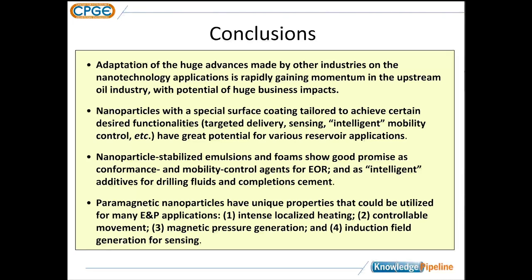Yeah, so that's a good question. In terms of the compressive strength, we believe what's taking place is that the nanoparticles are providing additional nucleation sites during the curing process, which helps get a little more order to the crystal structure at the molecular scale inside the cement, which improves the strength, although it's not entirely clear what that would be.